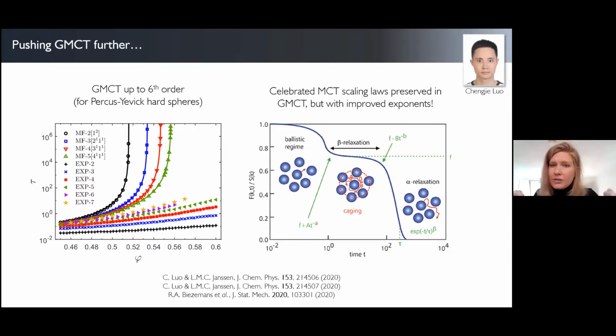And then you do a mode coupling calculation. You also get a curve like this, and you try to do the same fit with the same functions. Then you get a different a, b, and gamma, depending on the order of the closure. Yes. And then the fitted numbers from the simulation you compare with the fits from the mode coupling calculations.